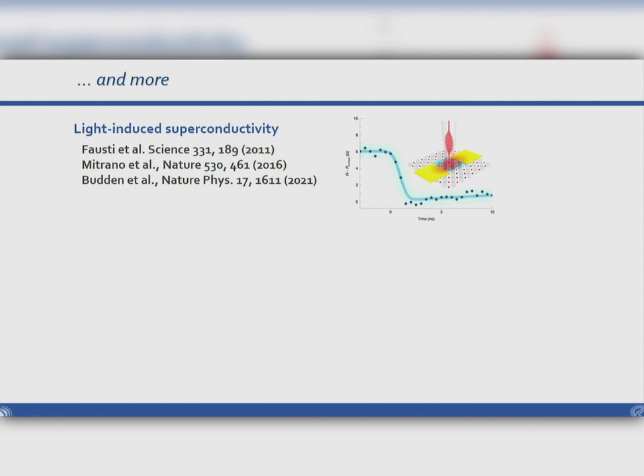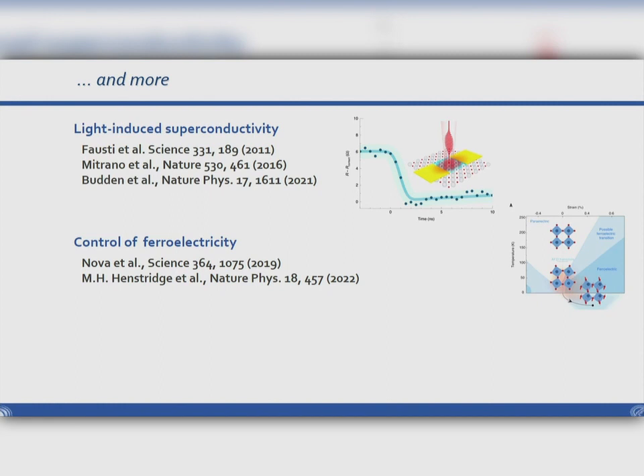First, I would like to highlight what we call light-induced superconductivity. So in these high-temperature superconductors, we have nowadays been able to achieve metastable, nanosecond-lived superconducting states far above the equilibrium critical temperature. Even at room temperature, we can achieve nanosecond lifetimes of a perfect superconductor. On the other hand, we are able to control ferroelectricity. So there's one example shown here. Strontium titanate is a quantum paraelectric, which in principle wants to become a ferroelectric material, but as you cool it down, quantum fluctuations prevent you from doing so, and we have shown that this particular type of phononic excitation can lead indeed to a metastable ferroelectric state also of this material.